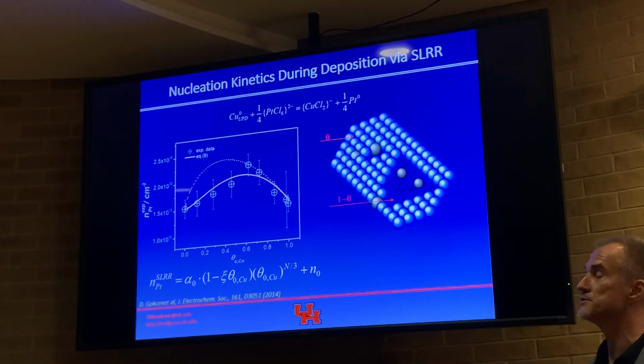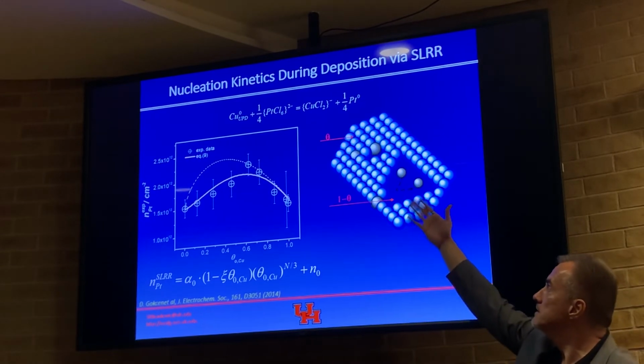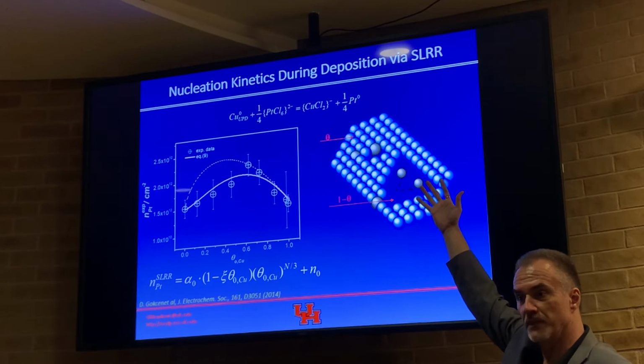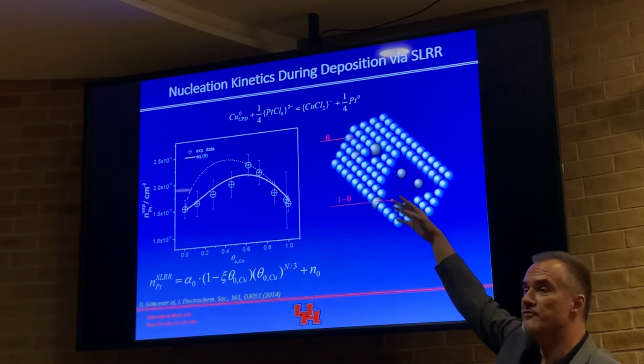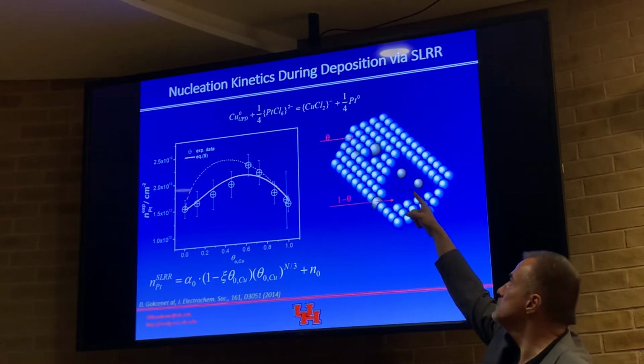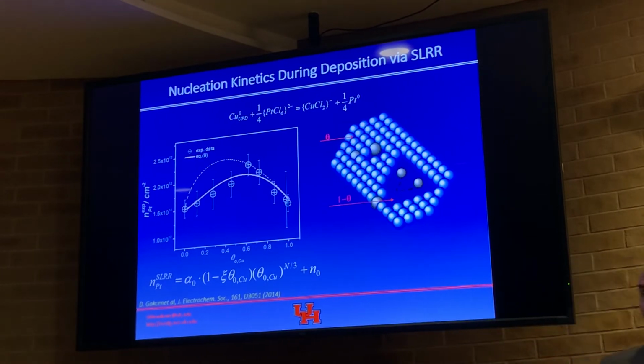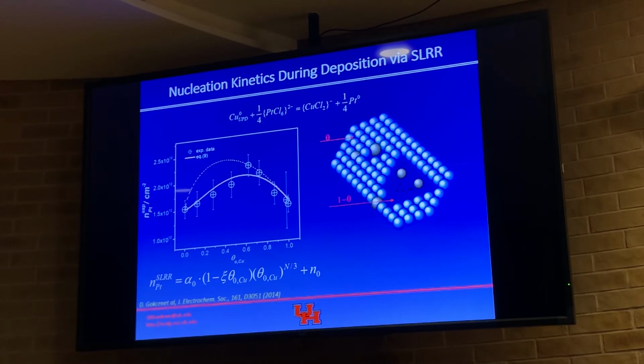Like what is on the picture. And then as you gradually start removing the rest because you're reducing, this guy will become free and eventually join the existing nucleus. So it's likely to be more involved in the growth part of the deposition rather than nucleation.